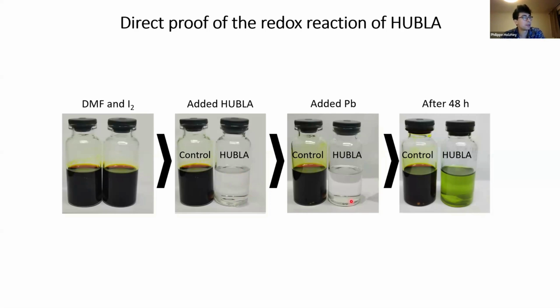And then we added a lead pellet to both. So it's a very thin lead pellet. And this lead pellet is then stirred. So this is the stirring bar over time. And then because it reacts with the iodide, it becomes lead iodide. And that's why it's turning slightly yellow over time. And in the control, really not much happens.